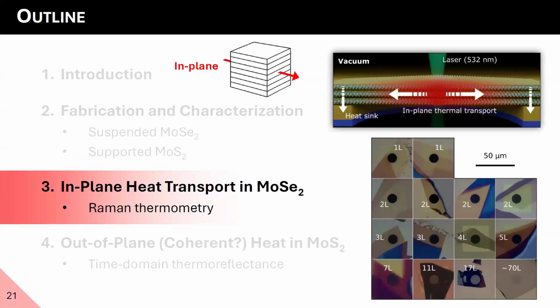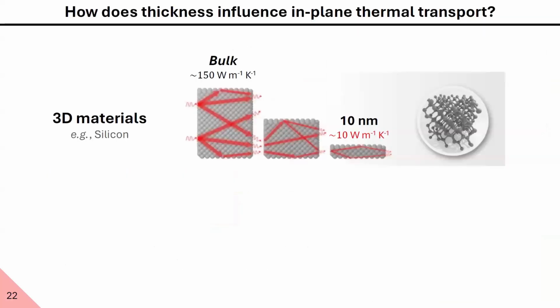With this, we reach our third section, where we perform in-plane heat transport experiments in our suspended molybdenum diselenide flakes with thickness control using Raman thermometry. So how does thickness influence thermal transport in 3D materials? These are our conventional materials, the ones we use every day in our lives, like silicon, the one we have in our chips. Here it is clear that decreasing the thickness of our conventional materials degrades their thermal transport properties. This is because we start having many more atoms at the surface as compared to the bulk, so the contribution from surface effects increases. We'll have larger phonon scattering at the boundaries, and therefore the thermal conductivity decreases significantly when we thin down our materials.